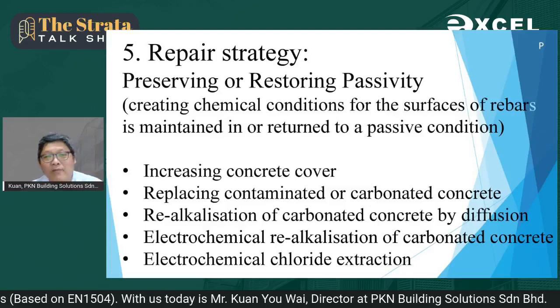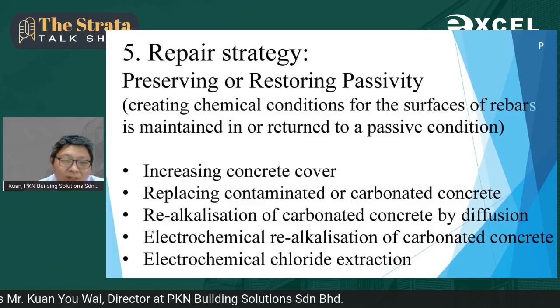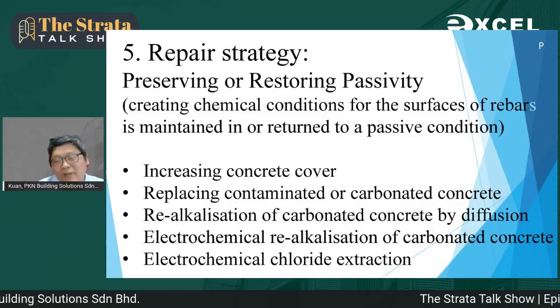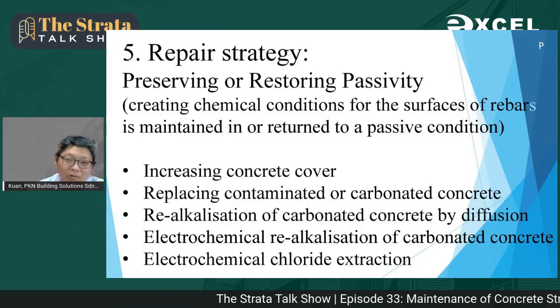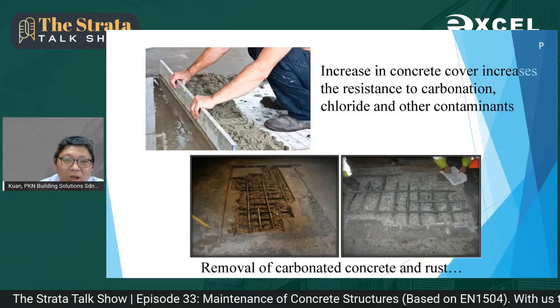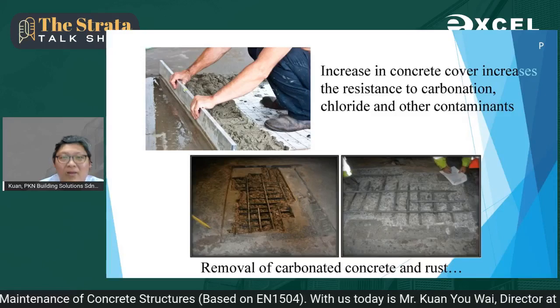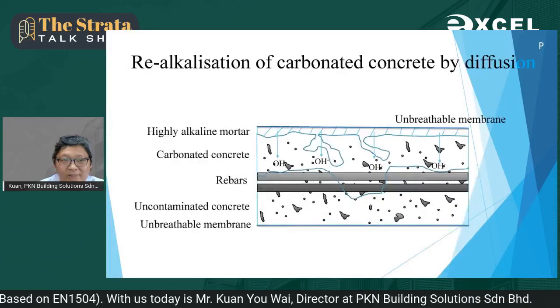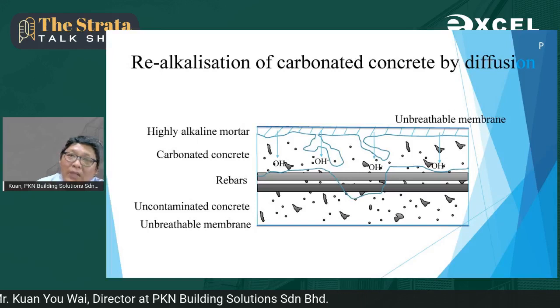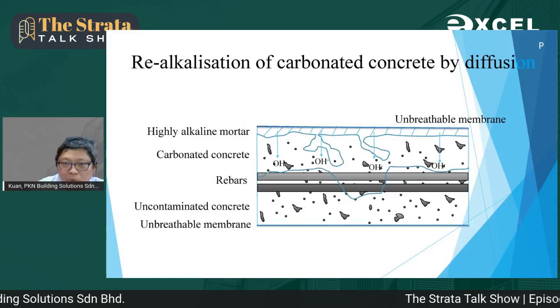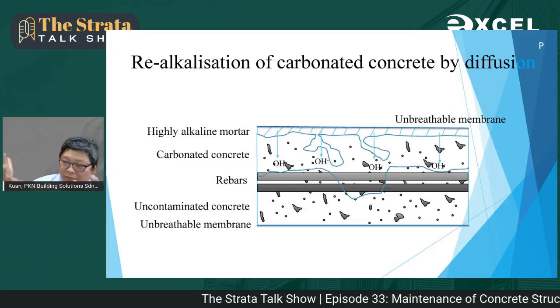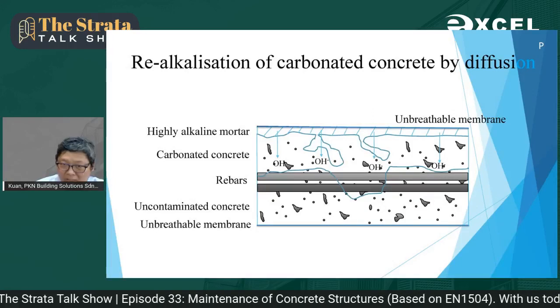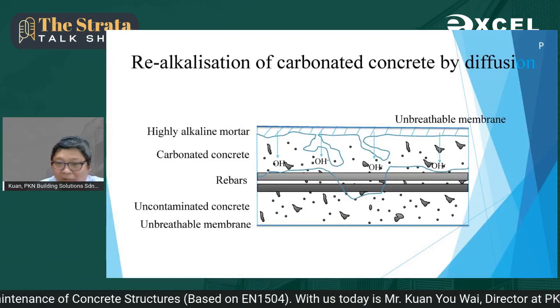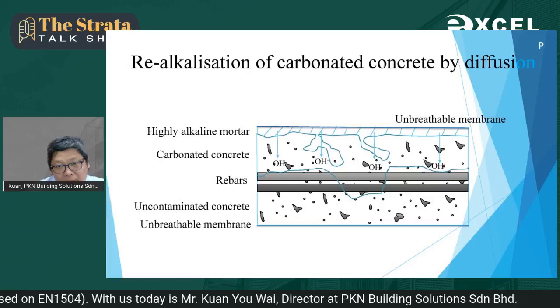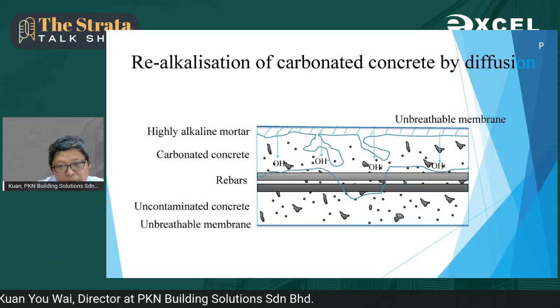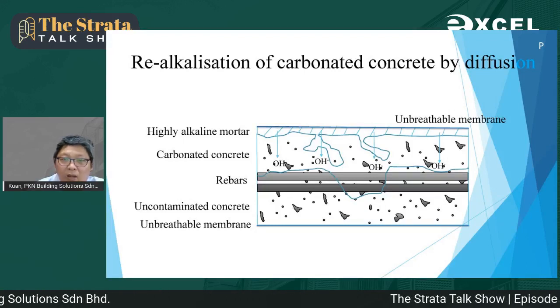So okay, we come to principle 5: how to preserve or restore passivity, how to return the pH of concrete, which has gone down due to the diffusion of carbon dioxide or carbonic acid or chloride. Okay, one of the ways is for the contaminated concrete to be removed and replaced. Another way is, of course, to increase the cement screed thickness. And if we can use liquid with very small molecular size particles, we actually can diffuse a high level of alkalinity into the concrete by way of gravity. This has been done very successfully by a lot of German companies, and yes, we also can do this based on our technology in Malaysia. So, by way of diffusion with highly alkaline liquid.